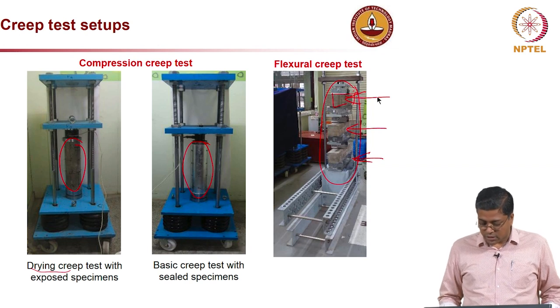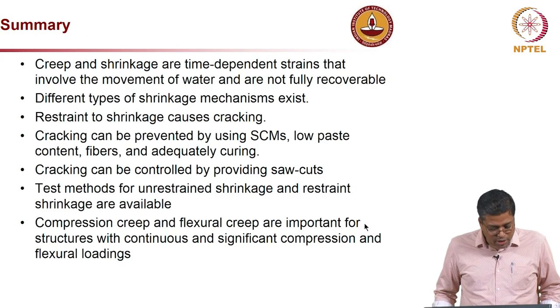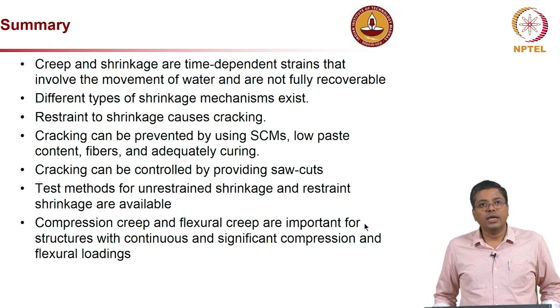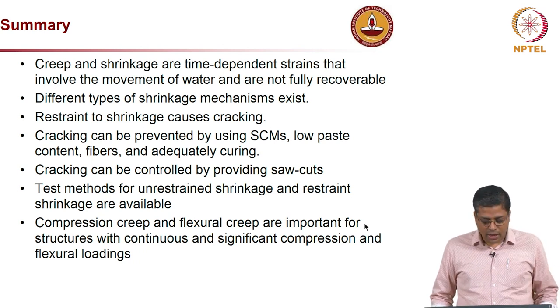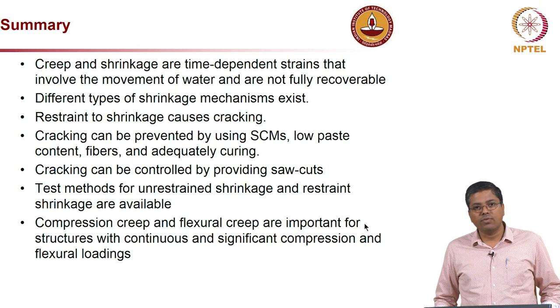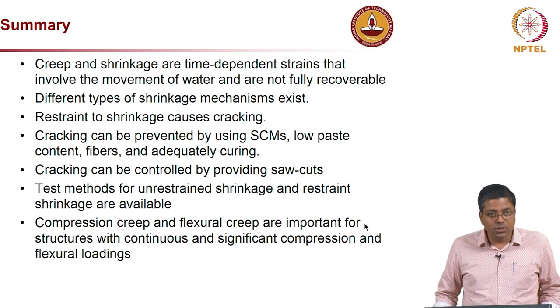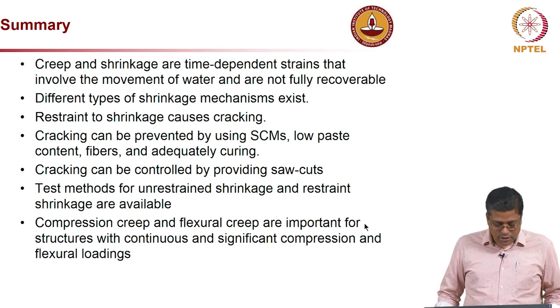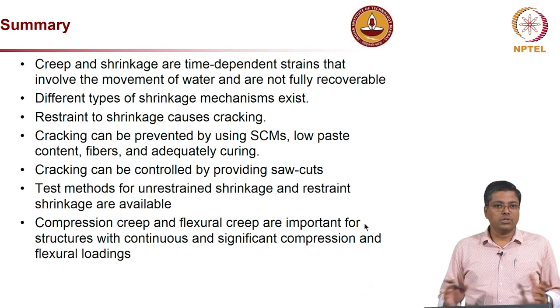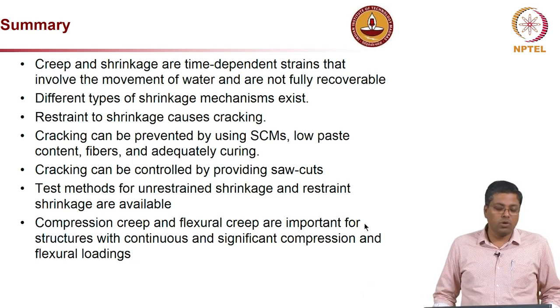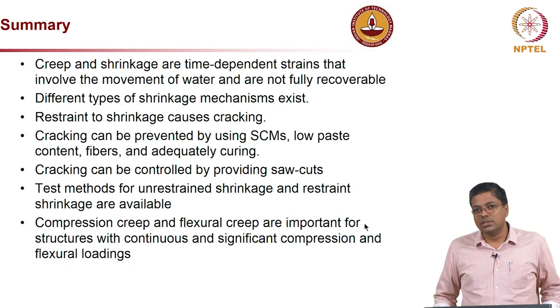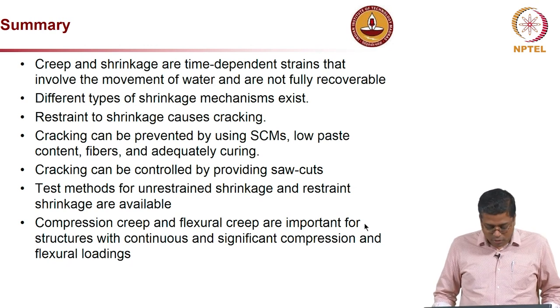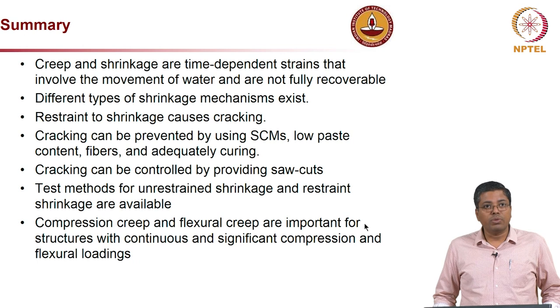Now, to summarize, we looked at creep and shrinkage and found that they are time dependent strains that involve movement of water and are not fully recoverable. And different types of shrinkage mechanisms exist. We looked at five different types, and restraint to shrinkage causes cracking. In other words, if there is no restraint, there will be only shrinkage but no cracking. But when concrete cracks, it is not good for the structure. So we want to prevent cracking.